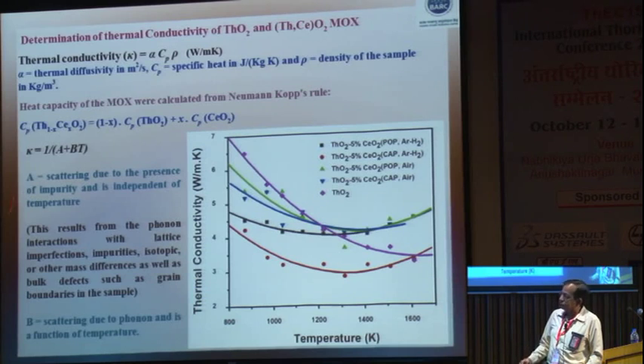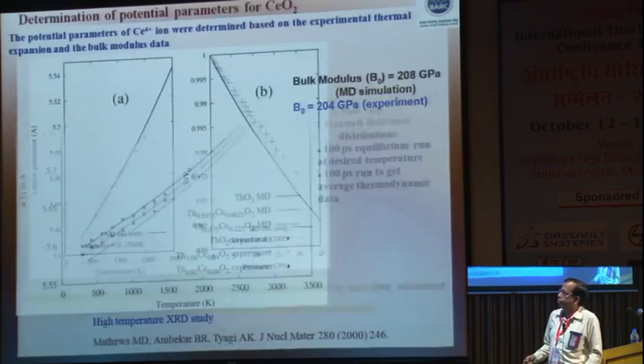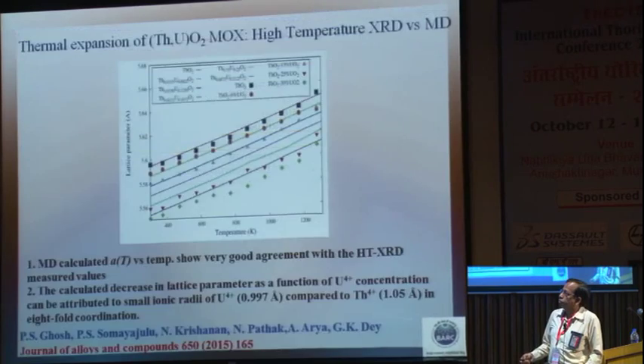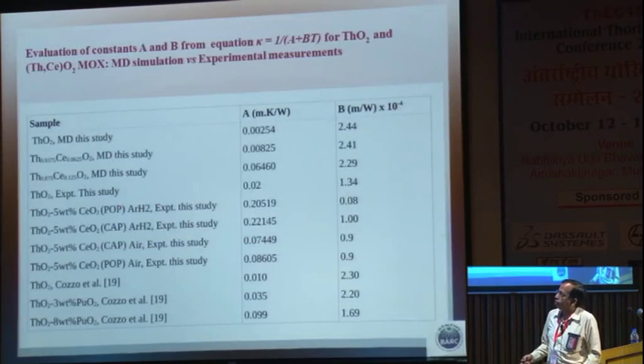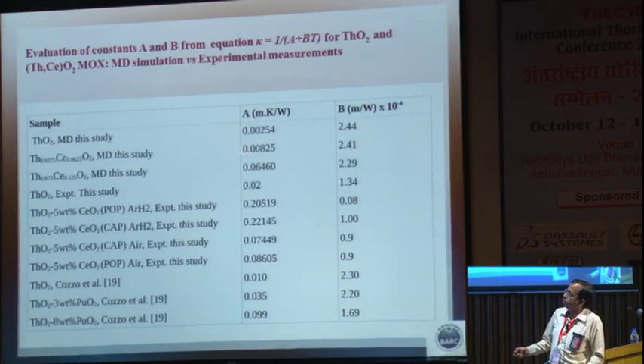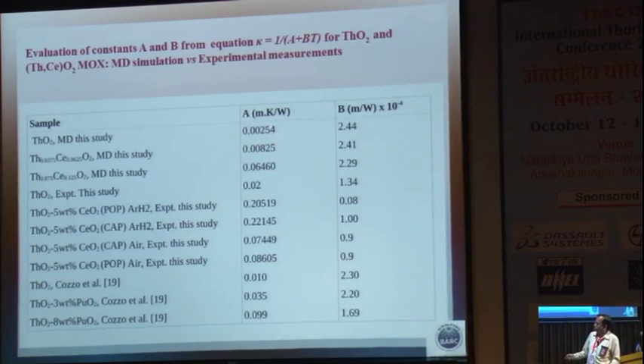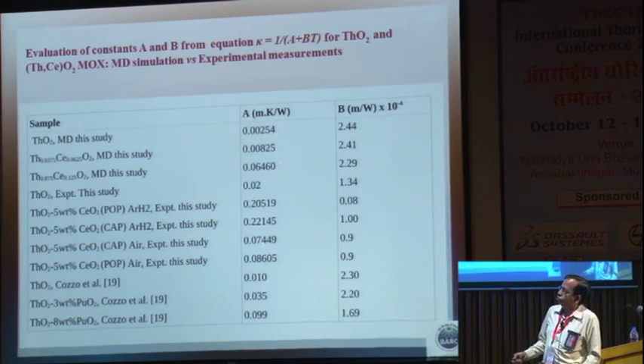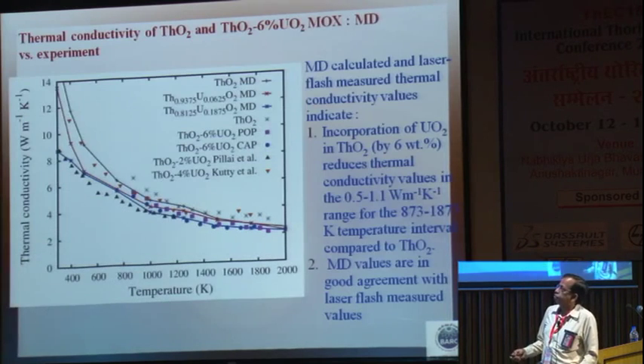Yeah, so this is the equation where thermal conductivity is expressed as A and B parameters, and the same is listed here for the different alloys, both evaluated experimentally as well as theoretically, and you can see that the agreements are reasonably good and they can substitute for each other. So this approach of MD simulation is very useful for calculating the parameters theoretically without doing any experiments, and can be extended to other types of mixed fuels.